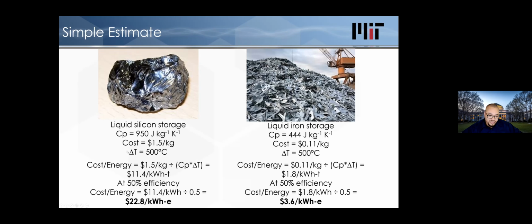Now imagine you swing silicon through a temperature swing, meaning you heat it up by 500 degrees and then let it cool back down 500 degrees. If you want to get the cost of that energy that you just stored, so to speak, in that process, that temperature swing, take the cost of the element, the cost of the material, divide by the amount of energy in that temperature swing. So that's $1.50 divided by CP delta T. And this comes out to only $11 per kilowatt hour.